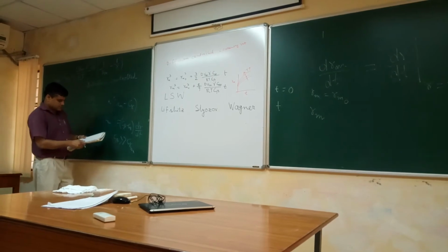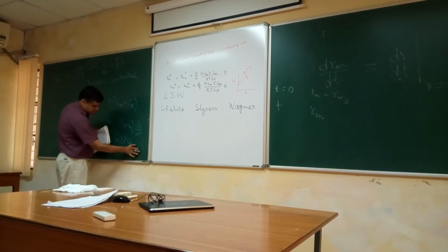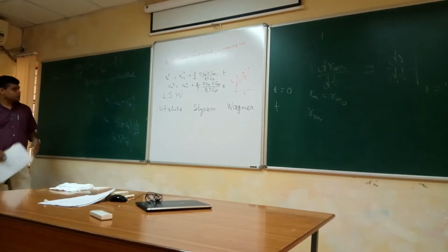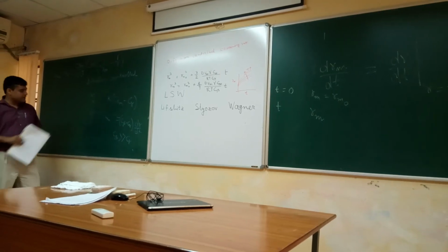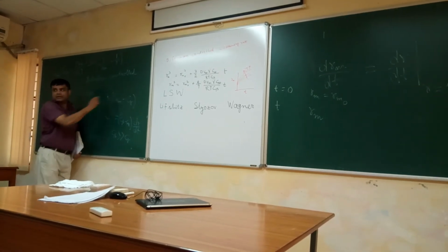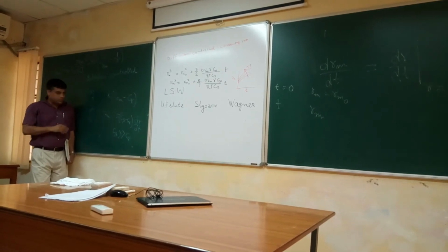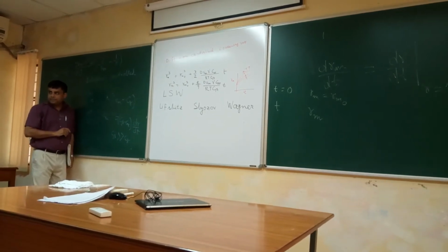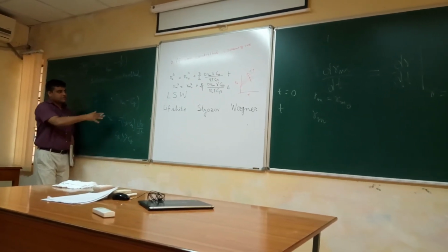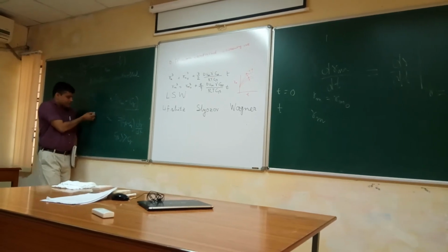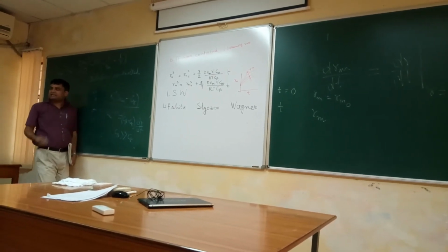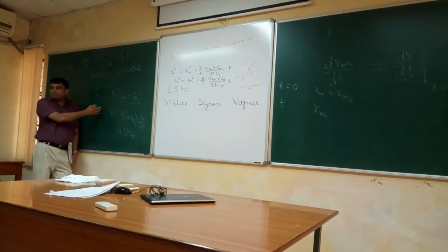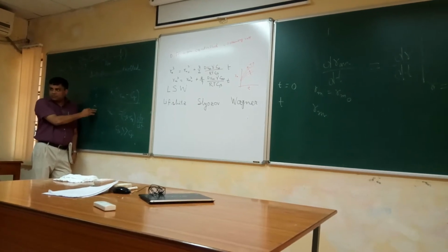So this is for diffusion control. Why diffusion control? If it is diffusion control, there will be a diffusion profile in the matrix. So in the matrix everywhere it is CRM. Why CRM minus CR? This is the driving force for atoms pumping inside. That is the number of atoms going per unit time, the flux of atoms that is going inside.